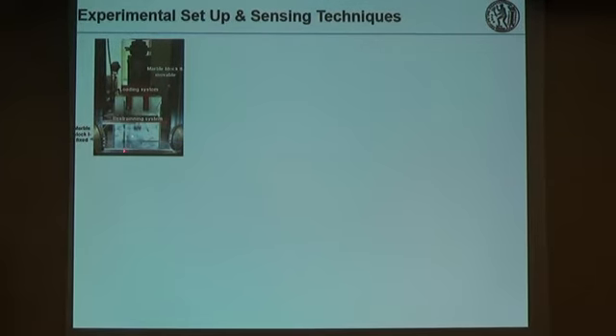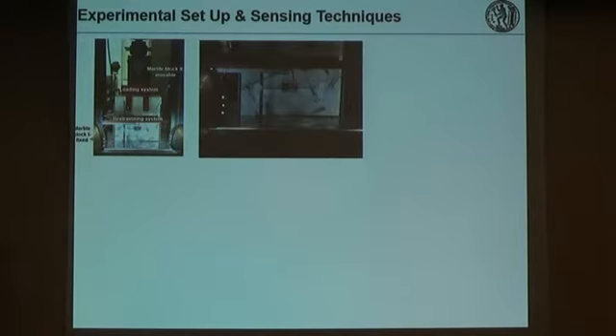During loading, marble block 1 was fixed, while an upwards displacement was induced at marble block 2 using a specially designed loading and restraining system. The experiment was performed using displacement control. Then the electrical resistance of the nano-reinforced mortar was monitored using the 4 electrodes. The 2 electrodes in the middle were used to measure the voltage, and the 2 outer electrodes were used to apply the direct current.